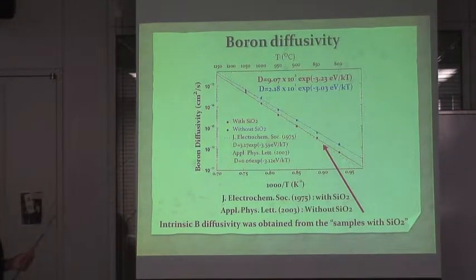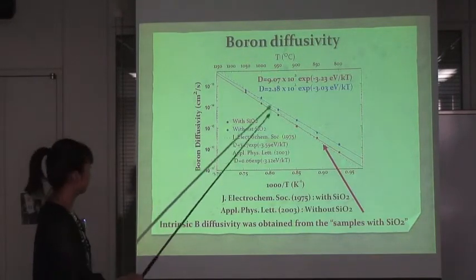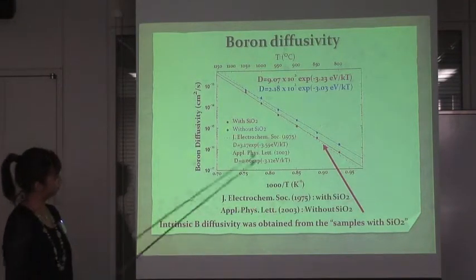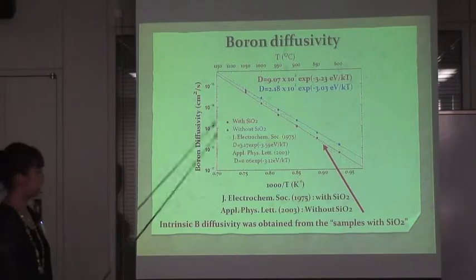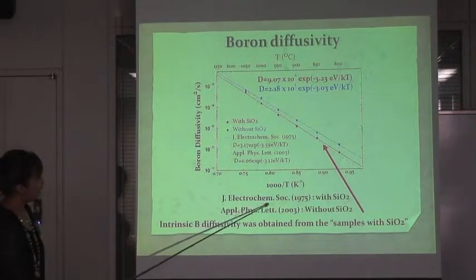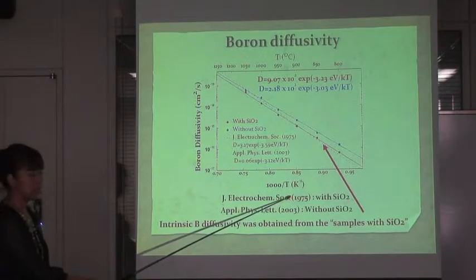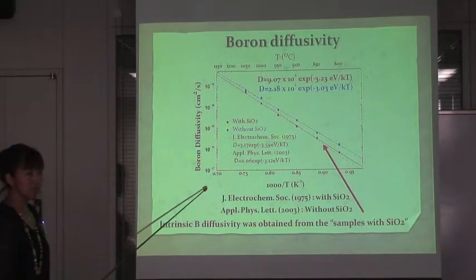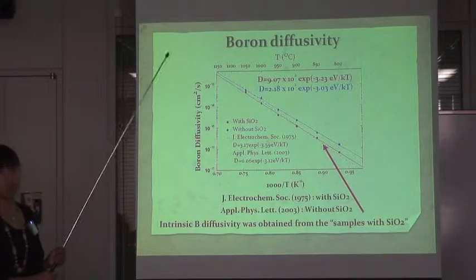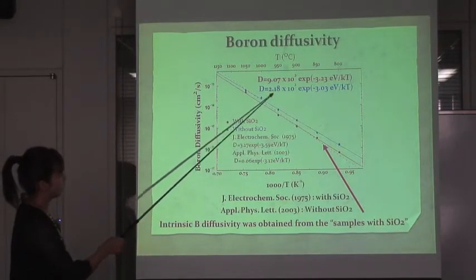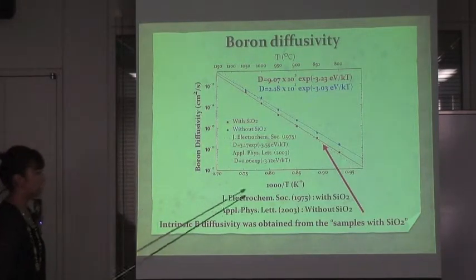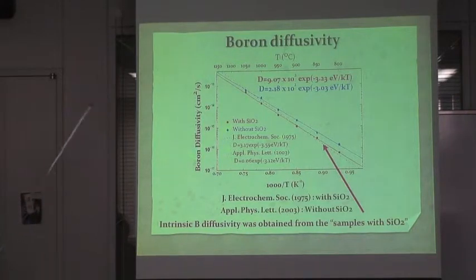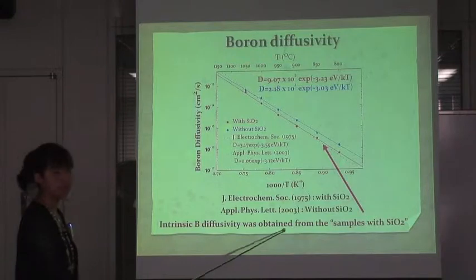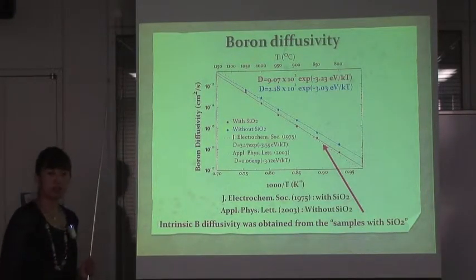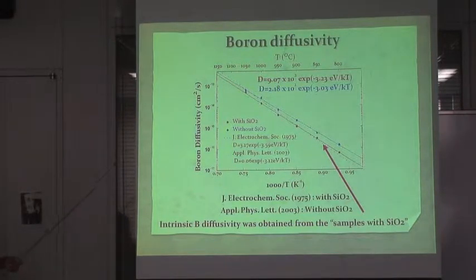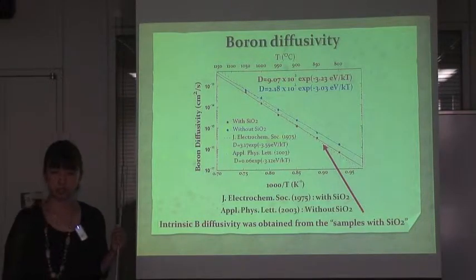And then, moreover, when our diffusivities are compared to the previous works, this red line, the with silicon dioxide result, agrees with the value reported in 1975, and the samples used for that study had silicon dioxide on the surface. On the other hand, this blue line, the without silicon dioxide result, agreed with this experimental value, and the samples used for that experiment had no silicon dioxide films on the surface. So what we can say here is that intrinsic boron diffusivity was obtained from the samples with silicon dioxide.